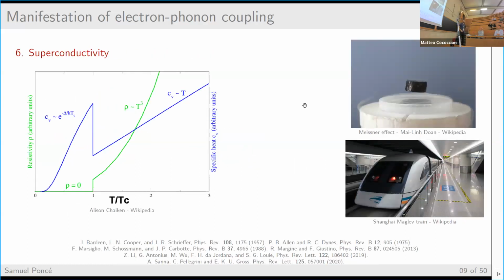Something that was mentioned by Professor Ginozzi was the fact that electron-phonon coupling is also responsible for standard phonon-assisted superconductivity. So here you are creating Cooper pairs, and then they can travel in the material without resistance. You have two effects in the case of superconductivity. One is that the magnetic field lines get expelled, which is explained by the Meissner effect, or the fact that you have levitation trains.